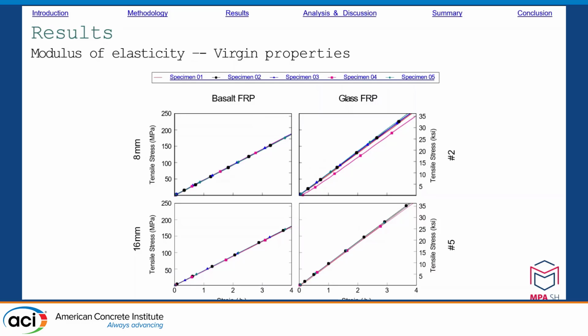The following graphs show the stress-strain curves of the specimens during the tensile test, which were recorded with the extensometer. The modulus of elasticity of the FRP bars can be calculated from these curves. All graphs show linearity, whereby the slope is higher for the glass fiber rods than for the basalt fiber rods, which is why the glass fiber rods have a higher modulus of elasticity. The measured modulus of elasticity for the glass fiber rods was around 66,000 megapascal and 46,000 megapascal for the basalt